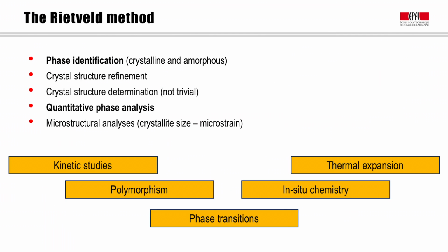The Rietveld method now finds its use in a wide variety of areas as a characterization technique for crystalline solids. Next to its use in quantitative phase analysis, the method can be used to derive or refine crystal structures for pure powder samples. Also, crystallite size and strain can be determined through peak shape analysis. In fact, many key properties of solid systems can be studied by Rietveld analysis.